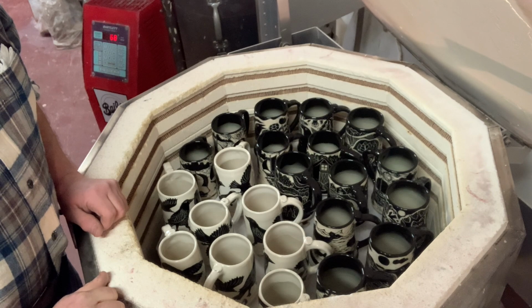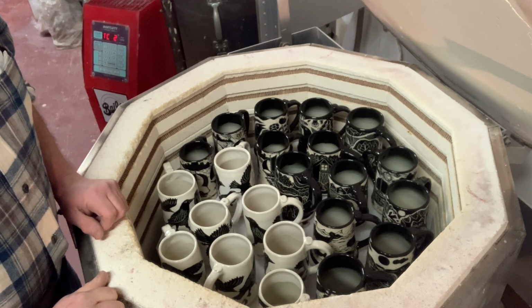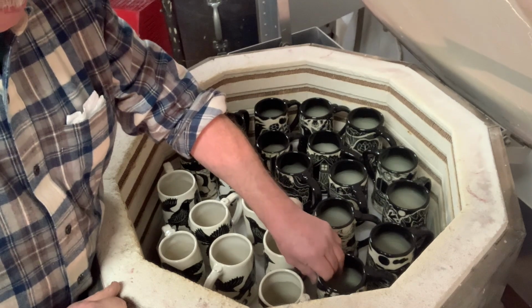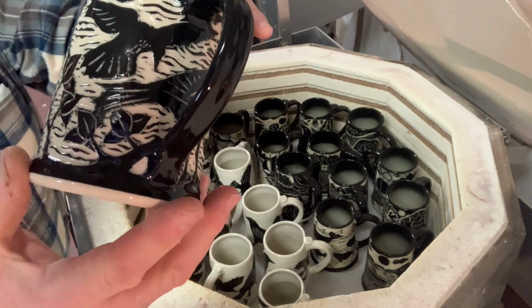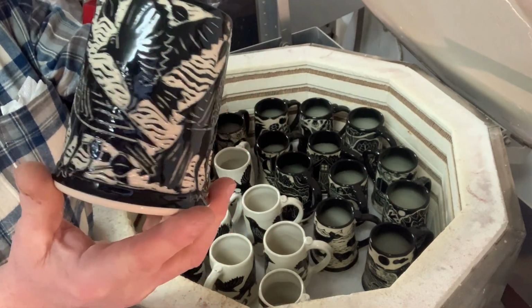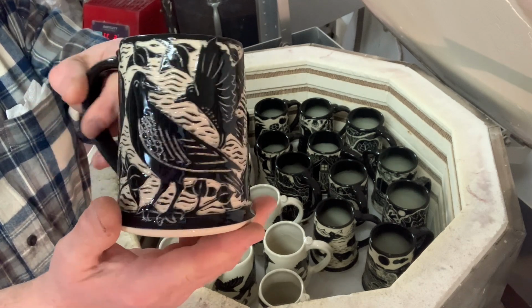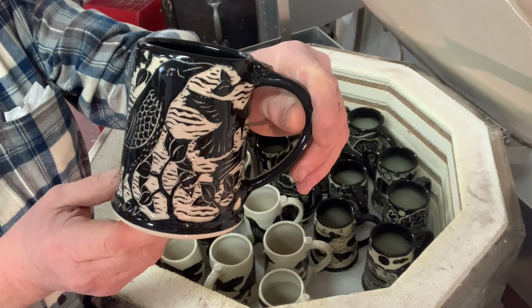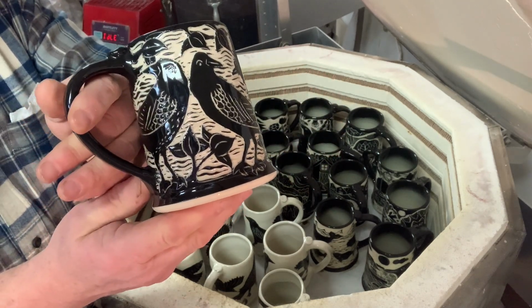Okay, I have a clear glaze cone 4 with sgraffito carving and stencil sgraffito carving pieces. So the sgraffito carving, I will show you each piece because they're actually each different. These are done with a black slip, and I thin the slip down, or it depends on how you look at that actually. I use black underglaze, LUG1 from Amaco, about 30%